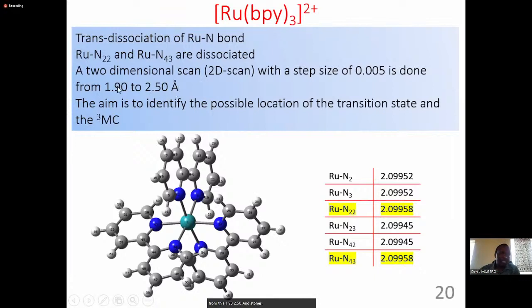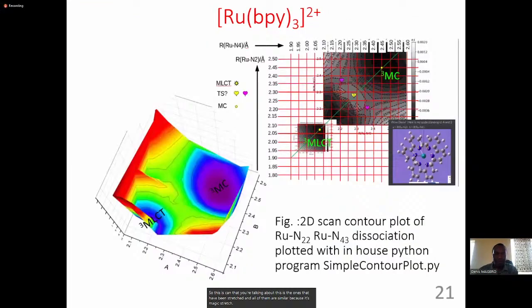This range is long enough to make sure that we cover the entire potential energy surface. And the aim of that scan is to be able to identify the triplet metal centered and to be able to identify the triplet transition state. So this is a scan that you're talking about. These are the bonds that have been stretched, and all of them are similar because it's symmetric stretch. And these are the results that we have.